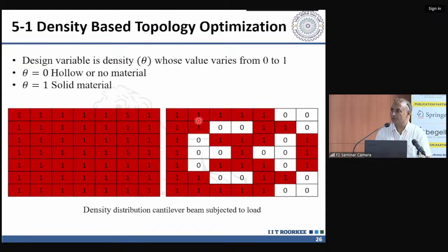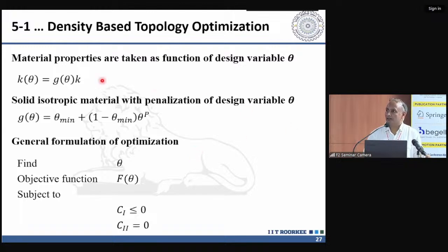For the optimization approach, we used a simple density based approach. One would represent material, 0 would represent hollow. But in numerical implementation, we can't go with 0. One is okay, but 0 could create a problem. So we'll modify that. The material properties would be written in terms of this density theta, our artificial density which we've introduced earlier. And this is where you would use a penalization approach. Theta would be taken as theta min instead of 0, so let's say a value of 10 to the power minus 3 or 10 to the power minus 4. That would be your representative of 0 to avoid problems in numerics.